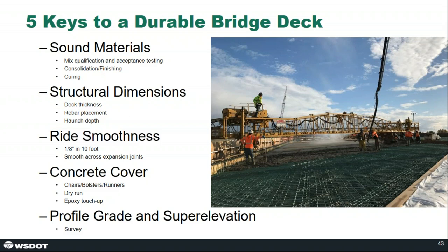Concrete cover is obviously key. The more cover you have, the longer time you have till the initiation of corrosion in your reinforcement. And lastly, profile grade and super elevation are important to achieve. It's important that this ties into getting a smooth ride across the bridge deck, and it also ensures that we're not creating any low spots that could lead to ponding on our bridge decks.